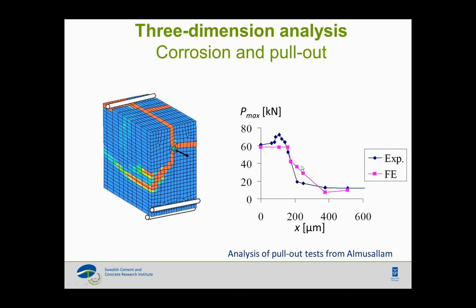What we got from our simulations based on the model that I just described is that we start by having a very good agreement in the beginning, but we did not include this positive impact of the swelling effect of corrosion for low amounts of corrosion. So we go with a straight line here, but as soon as we get to the cracking point, we capture this rapid drop in the pull-out force. So the model has been verified with very many different specimens, and that's one of those verifications.